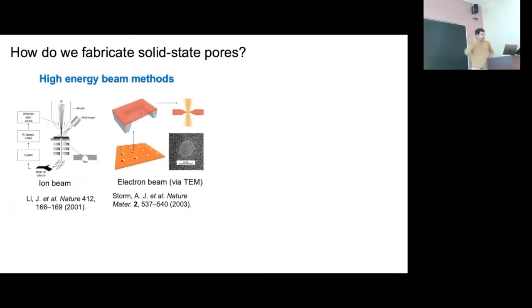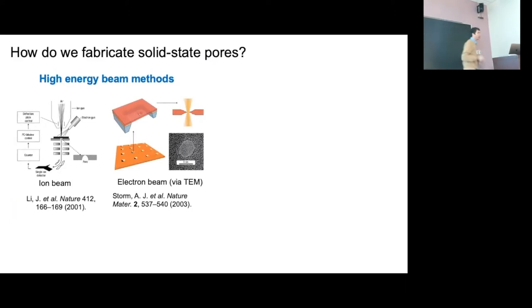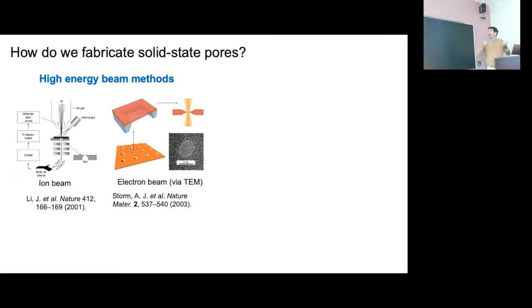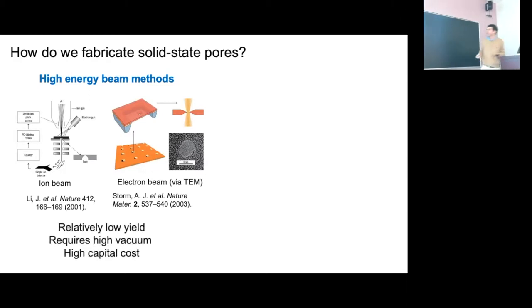The solid-state pore community tends to be very focused on construct work and doesn't often think at genome scale, which is surprising to me. The first topic: how do we actually make solid-state pores? A classic technique going back 20 years is to use energetic particles like ion beams or electrons. You take a membrane, put it in a transmission electron microscope, focus the beam, and make a pore. But there are obvious limitations — these are very expensive instruments, up to a million dollars, requiring clean room facilities and high vacuum.